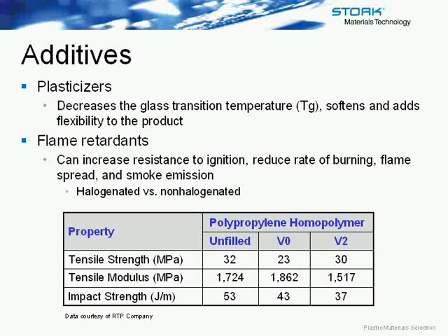For example, in the case of the flame retardant, as you can see in this table, the flame retardant packages result in an unexpected property change. You can see as the flame retardant material increases from unfilled to a V2, which is a very high-rated material, and a V0 as well, how the tensile strength is affected, as well as the modulus and the impact strength.